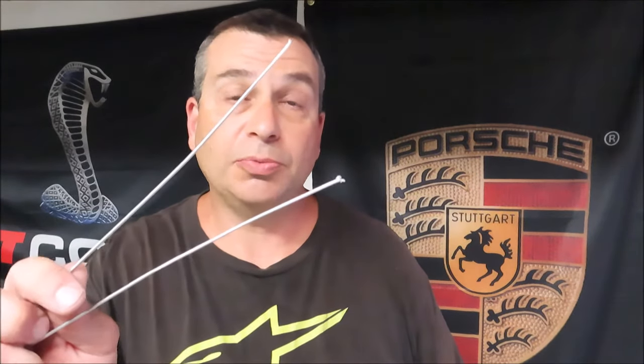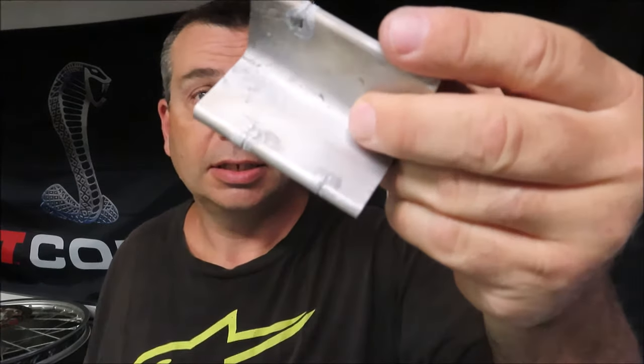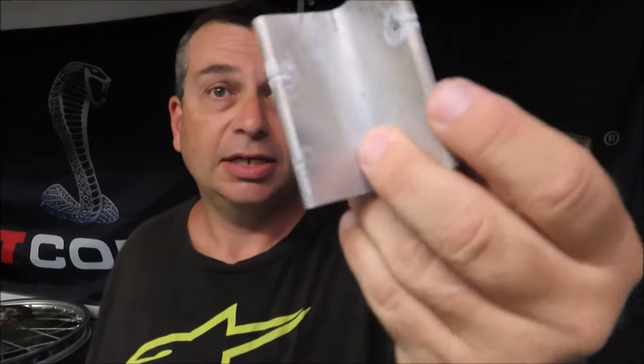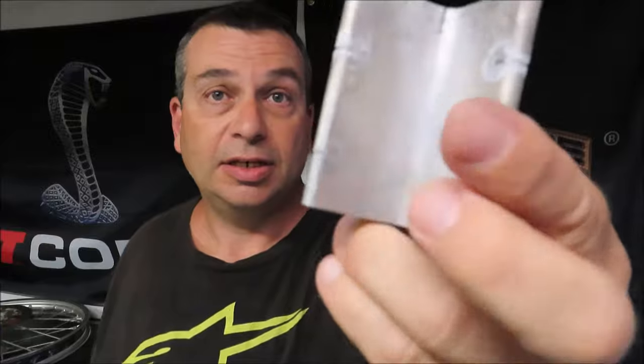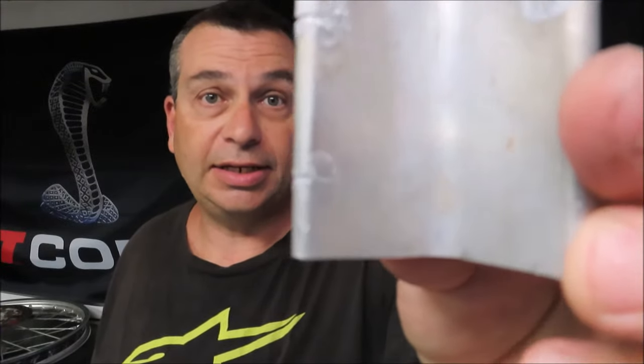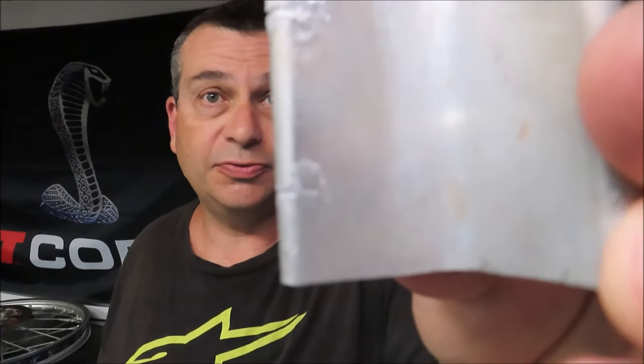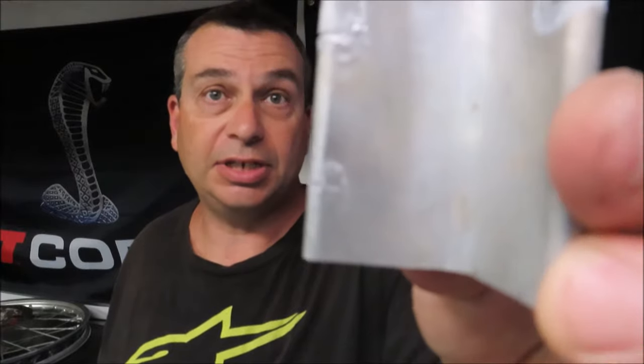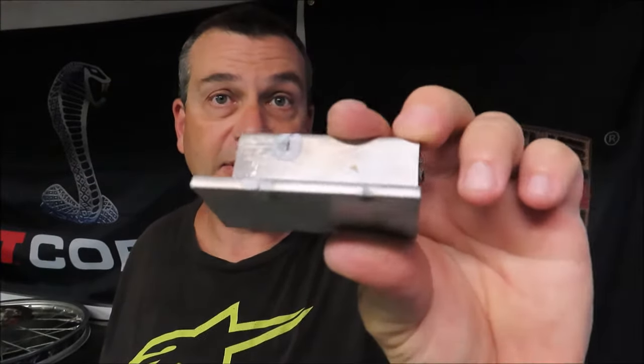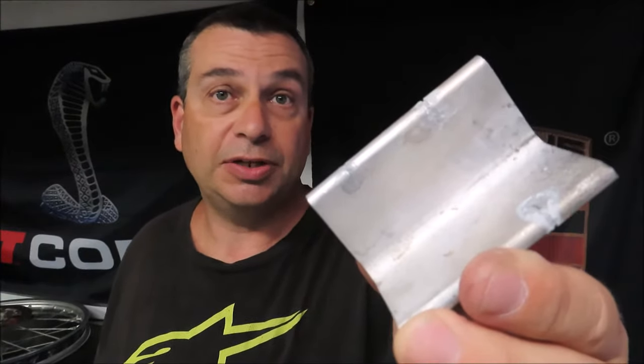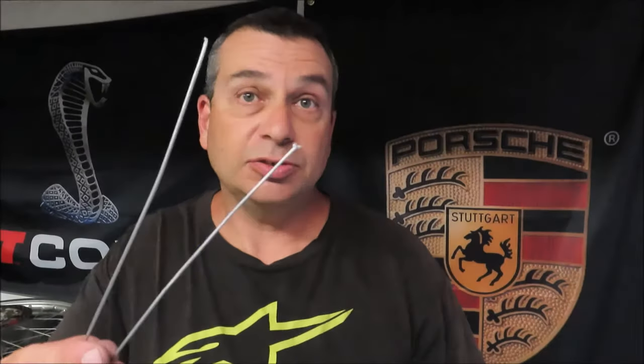Things started out good when I was running test runs with these aluminum welding rods. I had this piece of aluminum that I had cut some slits into with a hacksaw, and everything was going just fine. My third run, I was getting real good at it. As you can see, it sealed the void up pretty nicely. I didn't bother cleaning it up at all or sanding it, but it seemed like it would work just perfectly on the wheel. So after testing out the aluminum welding rods, I thought for sure it would be able to fix that small crack I had in the wheel. But as you saw, things did not go according to plan.